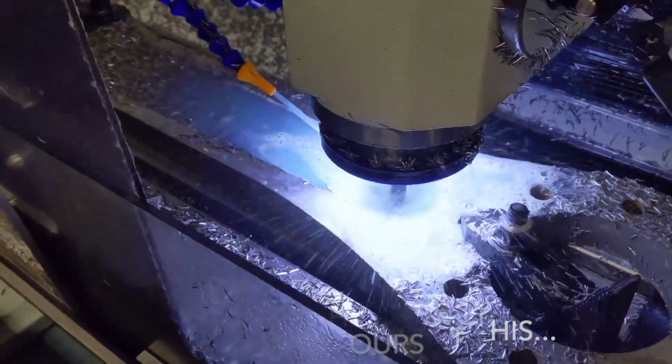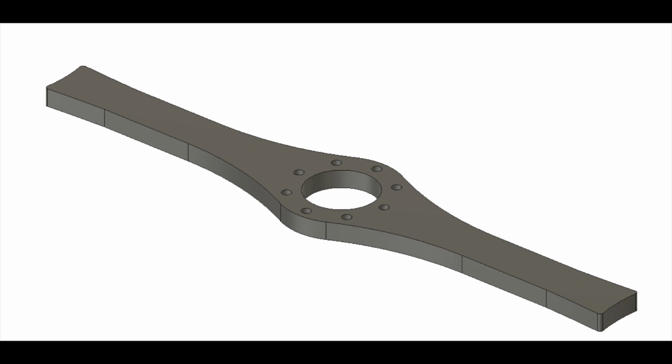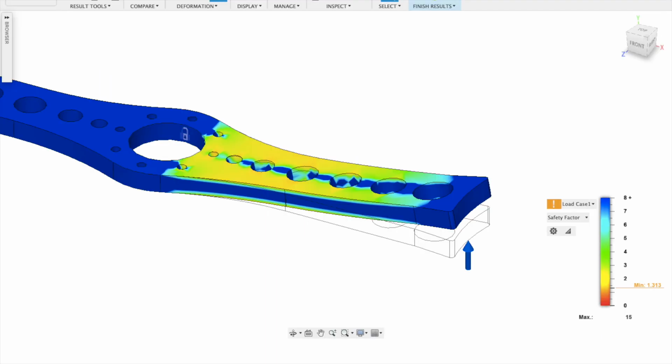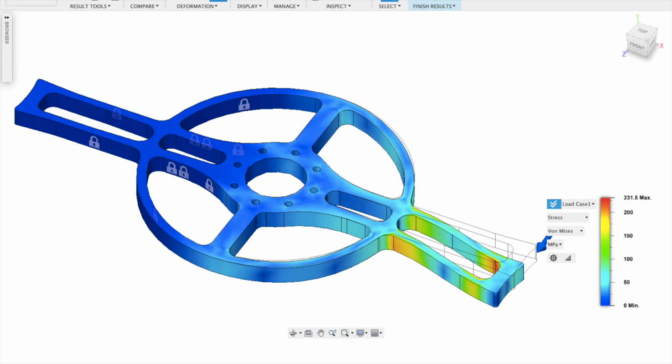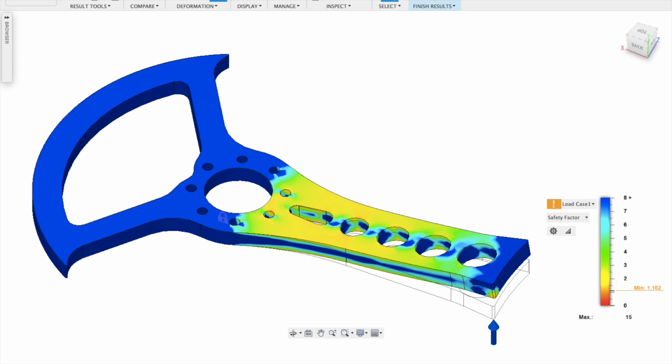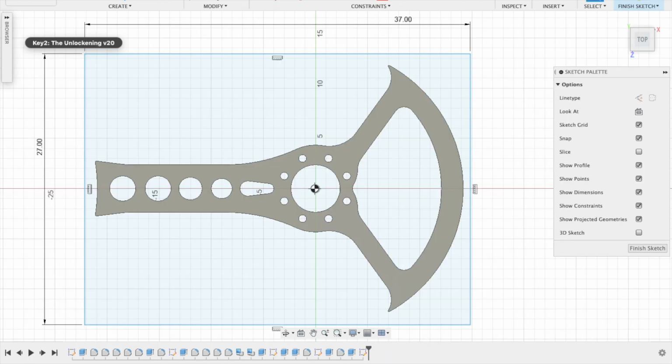AR-500 comes already hard. So we're left either needing to make the whole bar narrower, sacrificing horizontal strength, or cut weight using through holes. Unfortunately, none of the AR bar designs we drew up could match the strength and stiffness of the THICC Bar without making major sacrifices on stability or cost, neither of which we were willing to compromise. A thicker AR-500 key is an option which eases the compromise between stability and strength, but it's also more expensive to make, and there's another problem, hardness.